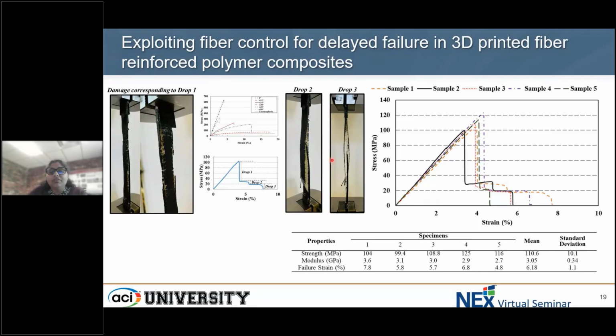So in particular, if you see the strength and strains of the discrete fiber orientations, so the orientations that just had the 0, 12, 24 and all that, when combined this way, definitely the behavior is different. The strengths for 0 degrees are somewhere around 600 MPa. However, for 12 degrees, they are lower. When you have combined it in a composite, they're even lower. So definitely there are differences between the single fiber and a combined kind of composite. So the important thing was to understand how does this composite behave in a perfect situation or a perfect bond situation. How would this composite really behave?